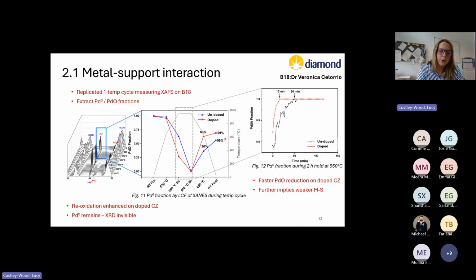If we now highlight this 2-hour period at 950 degrees and watch the reduction from this point to this point, looking at the fraction of palladium metal, we see that the reduction of palladium oxide is much faster on our doped ceria zirconia, which again confirms this weakened metal support interaction, where the palladium nanoparticles are more mobile and less anchored and therefore easier to reduce.